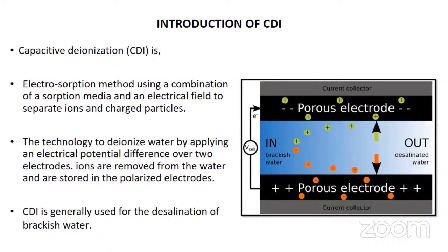The adsorption capacity and electric conductivity of the electrode highly depend on the electrode material. For high performance of the CDI, carbon is the choice as porous electrode material. The specific surface area and pore size distribution improve the high salt electrosorption capacity. Furthermore, the material used should be stable, with no chemical degradation of the electrode in the voltage window applied for CDI. Lastly, the cost of the electrode material is important to take into consideration. Nowadays, activated carbon is the commonly used material because it is the most cost effective and has a high specific surface area.